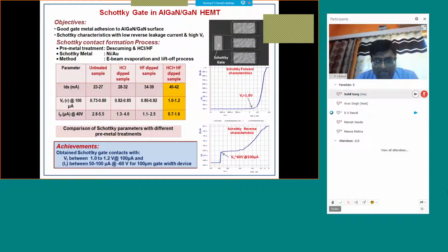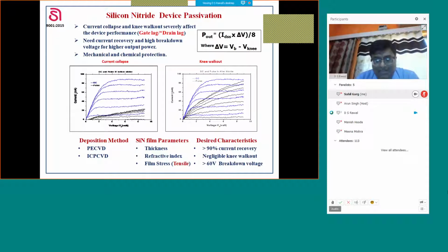We are using nickel Schottky gate, and the barrier height is of the order of 0.9 electron volt with the breakdown voltage of more than 150 volts. Another important process, as discussed that day by Professor Dipankar Shah, is device passivation, because this gallium nitride material is a very, very defective material. So traps are there. These traps normally don't participate when we are doing DC characterization, but they come into the picture during RF performance. So this trap characterization is normally carried out by pulse IV.